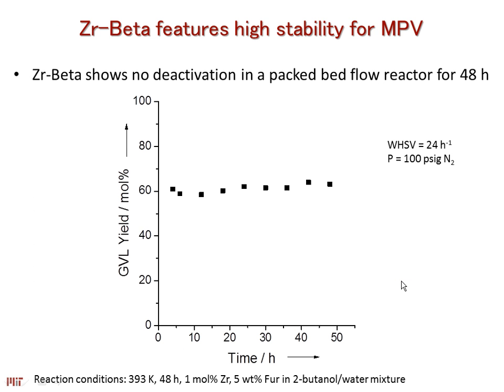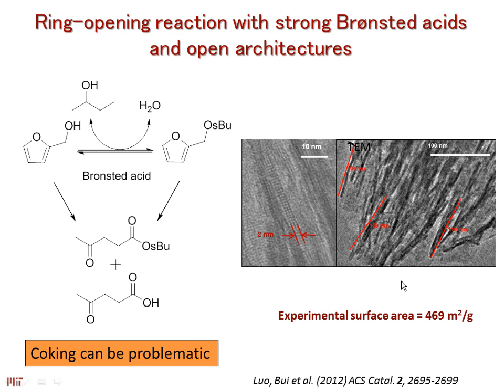Usually the way we operate, we always do a lot of reactions in batch, and then we move to our flow systems to look in a little bit more detail at the stability of the catalyst, at the kinetics. In this case, for example, we run at 60% conversion in a flow system, make sure that our catalyst doesn't deactivate for this transfer hydrogenation step, and from there we move into the coupling. For example, what can we do now that we have our furfuryl alcohol and we know that we can produce these levulinate derivatives or convert them into GVL? We wanted to start coupling this with our Bronsted acid step where we open this up.